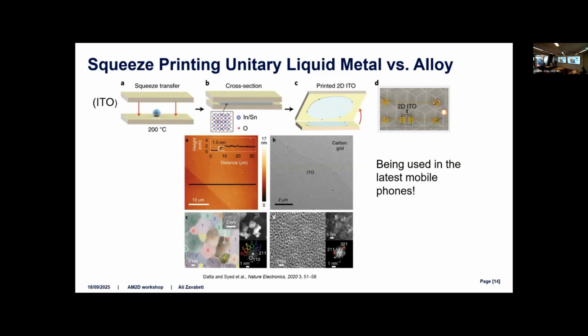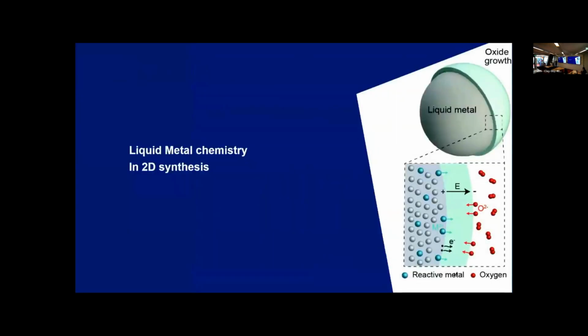We used a touch screen in our publication, and this is being used in a different style. In industry, like Apple and Samsung, apparently they used to have a glass inverted and float onto liquid indium and then sputter tin on top to make ITO. However, they have changed their process slightly to just melt it together with indium instead of sputtering. So this is an adopted technology at the moment. And then there is also chemistry involved with liquid metal. It's not just mixing two metals and getting a complete mixture.